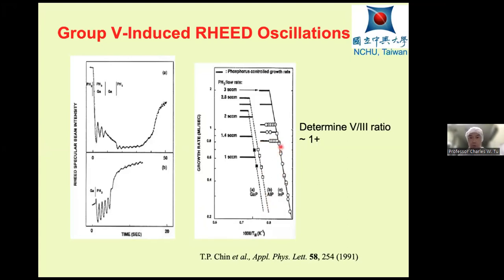We want to grow at a V/III ratio slightly greater than 1, because if it is less than 1, we have an excess amount of group 3 atoms on the surface, and the surface becomes rough. So this is the condition we want. That's how we determine our growth.